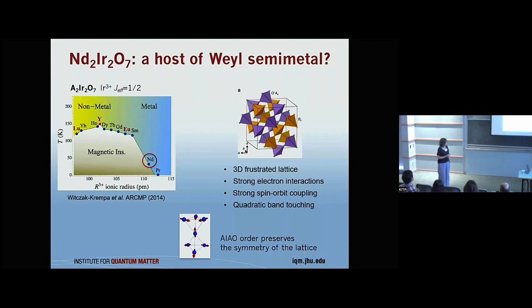Iridates are very interesting also from the point of view of electronic band structure. This is a phase diagram which describes the interest, which I would say is somewhat outdated. A is the rare earth, B is the iridium site, and this phase diagram shows that it's a semi-metal; at that point it was not metal. Now I think the consensus is semi-metal with some interesting topological band which could appear in what was at first recognized as an insulating state.